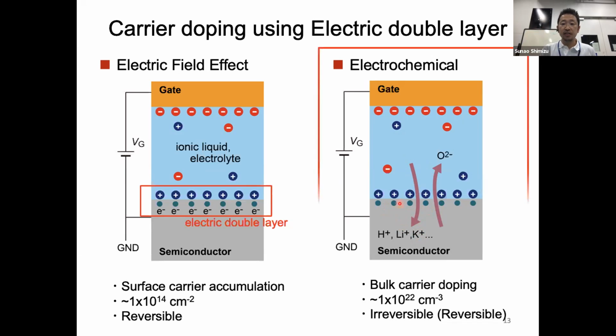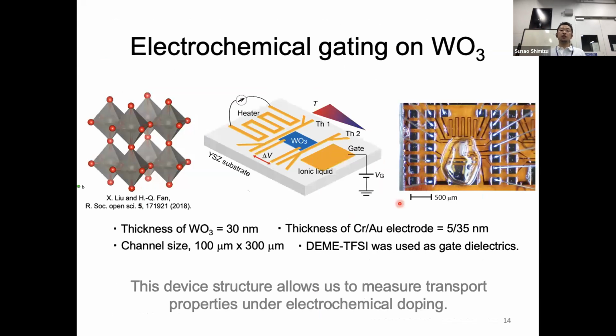By using this technique, we controlled the physical properties of tungsten oxide. This figure is the crystal structure of tungsten oxide. As you can see here, there is a lot of void space, so probably it is easy to intercalate some ions or remove oxygens from this structure. And this picture is a schematic picture of the device structure. Here we put a tungsten oxide thin film, and here is a gate electrode. We put ionic liquid to cover both the tungsten oxide and the gate electrode. And by changing gate voltage, we can control the carrier density in the tungsten oxide thin film.